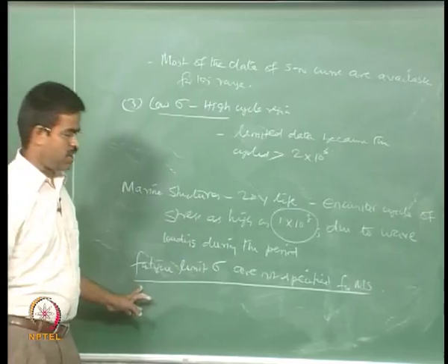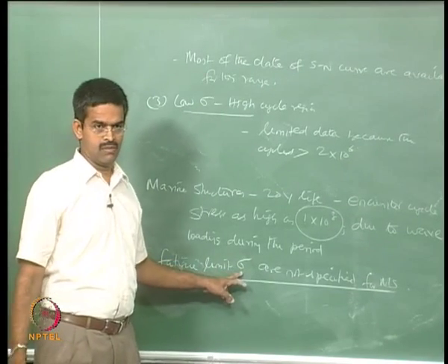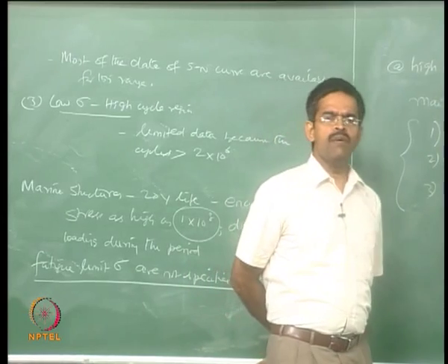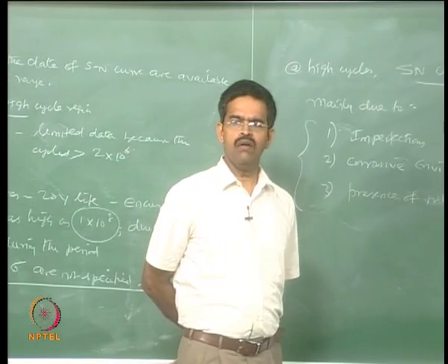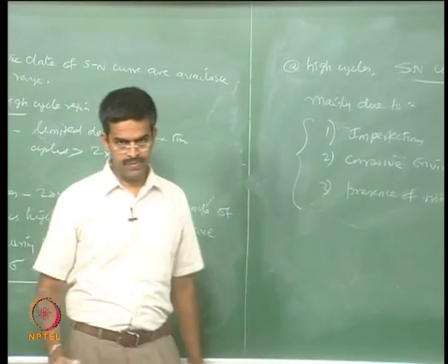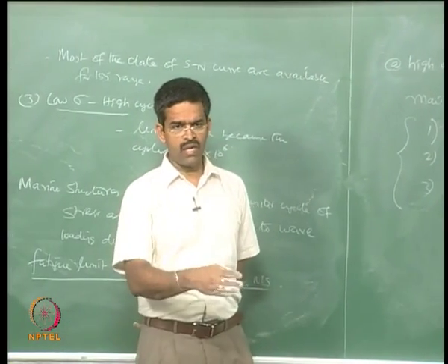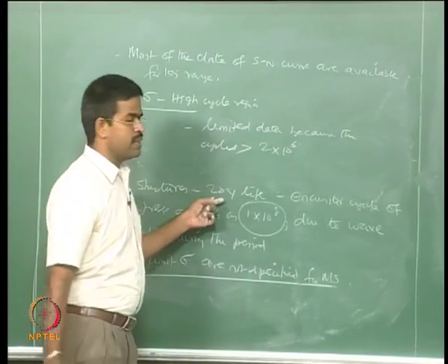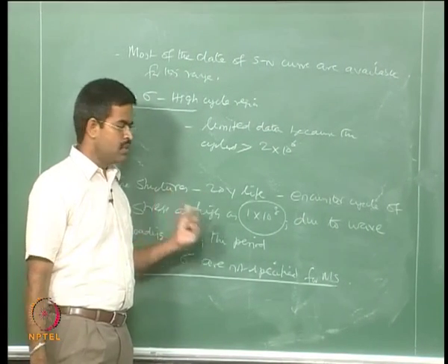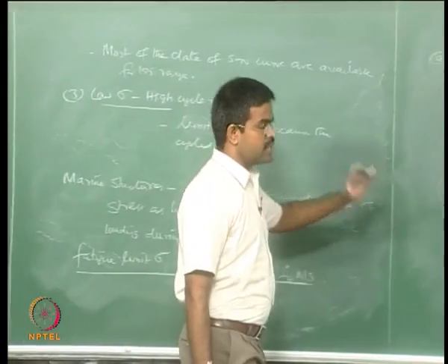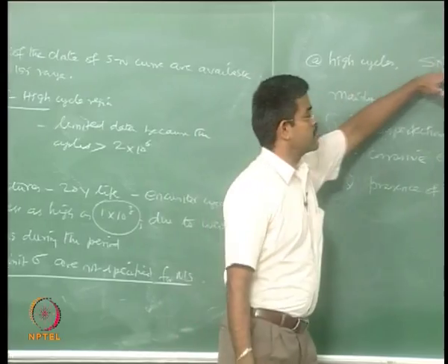Codes do not specify fatigue limit stresses for marine structures. So, fatigue damage estimate will always be done for a cycle more or less than 2 × 10^6, wherein SN curves are available. But in reality, for a period of let us say 15-20 years lifetime of a marine structure, the cycles are very high. Added to it, it is seen in the literature that the SN curve actually drops.